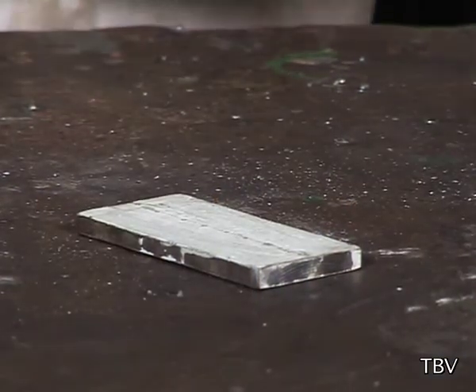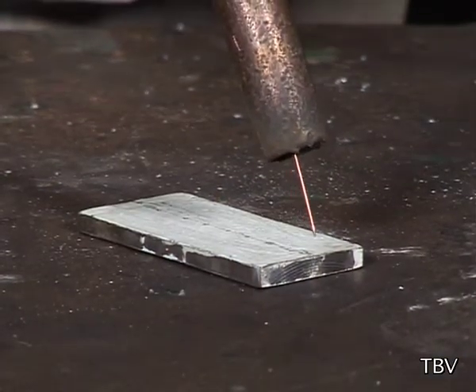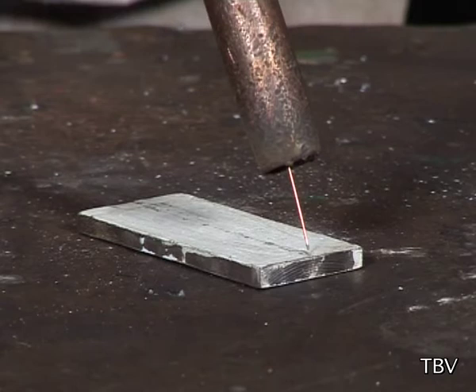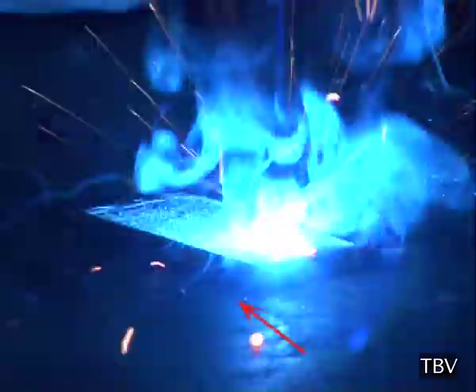Set the workpiece in a flat position on the table. Hold the torch at an angle of 10 to 15 degrees to the punched line of the workpiece. Open the CO2 gas flow and electrode wire before striking the arc. Strike the arc. Maintain a filler wire stickout of 8 to 10 mm from the end of the contact tip to the job as required for dip transfer mode.